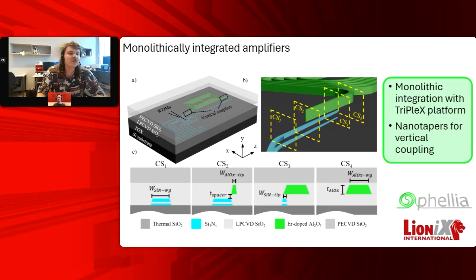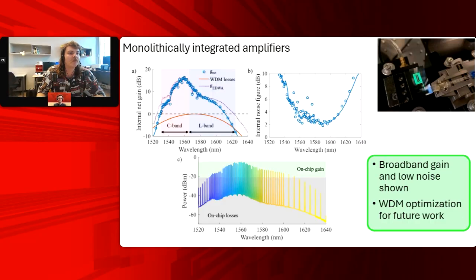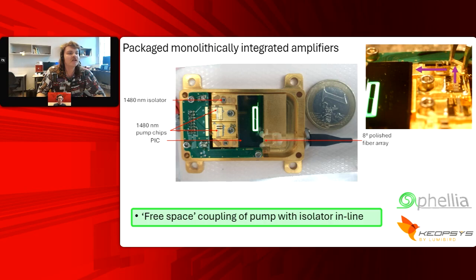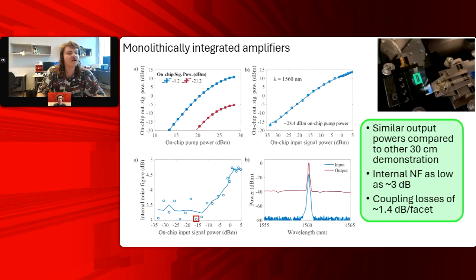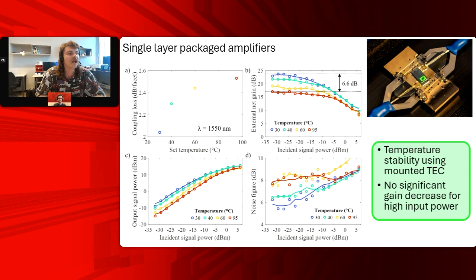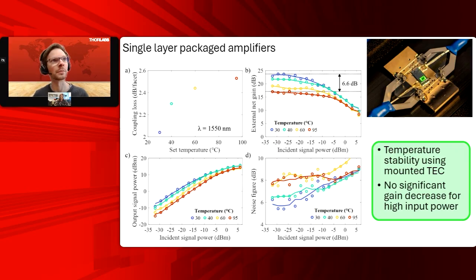I think the measurements I was showing of the thermal operation, where we get really low differences in the gain as we heat up the devices, are a hallmark of this. We don't really have a lot of thermal problems. As I mentioned, we don't cool the chips as we pump them. People out there in the SOA world would shake their fist at that, because they have to have their devices on a heat sink and be actively cooling them while they do their gain operation, which we don't need to do. Mm-hmm. I think that is an extremely impressive result, especially since I remember melting a piece of tape that one of my silicon chips was mounted to using one of the micro heaters, but I think I was putting a little too much power through that.